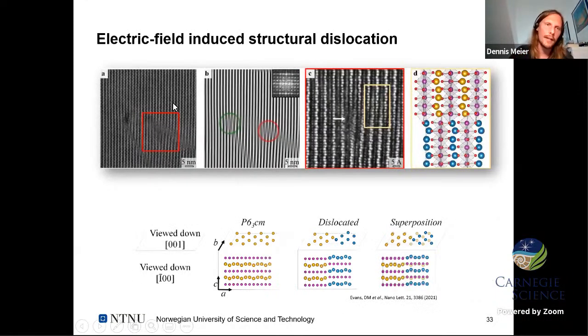What you see on the left-hand side is the zoom into the region under the tip, and you see that there is now this dislocated structure. There are the erbium columns which somehow stop and then merge with manganese. So wherever we apply the electric field, these types of defects now occur. Looking at the Fourier transform, you can see that there are now dislocations in this area, which lead to the fact that we no longer have perfect manganese and erbium layers, as you see here in figure C, where we zoom in.